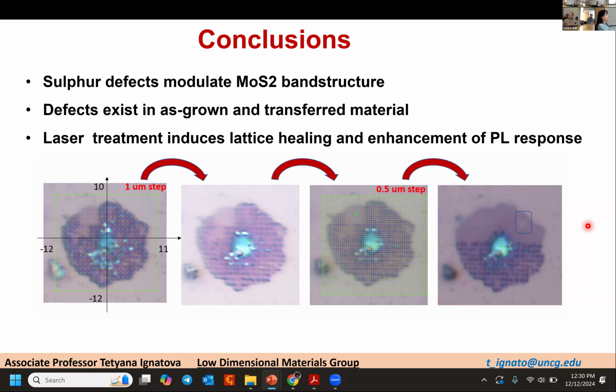But certainly, I agree, you can change this material. I totally agree. But what brought us to our conclusions is that we always see the same shift. I showed only one correlation plot, but we always have very similar results. It really depends on the number of defects, or if the sample is fresh or aged. Then the ranges will be differently split. But I totally agree. We definitely look for vacuum Raman analysis in order to make conclusions.